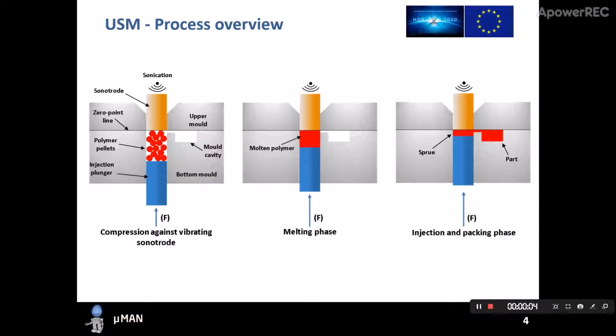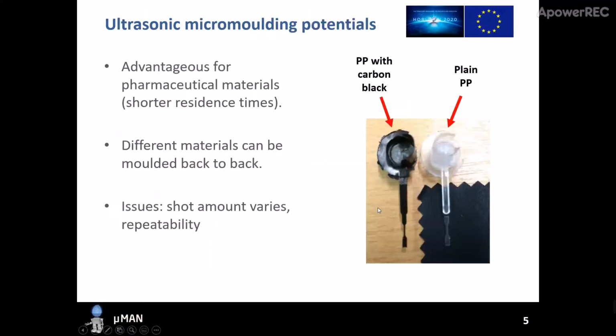This is the overview of the ultrasonic molding process, or ultrasonic micromoulding process. We have our sonotrode at a fixed position, and we have our upper mold and bottom mold here, and we also have the polymer pellets inside our sonication chamber, and we have our injection plunger at the bottom, and we compress these polymer pellets with some force against the vibrating sonotrode for melting the material. So as you can see, the polymer pellets are being melted, and we apply some further force, and then we are able to inject the polymer melt into our micromoulding cavity.